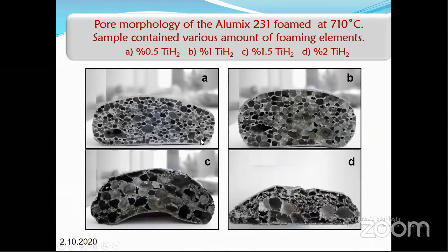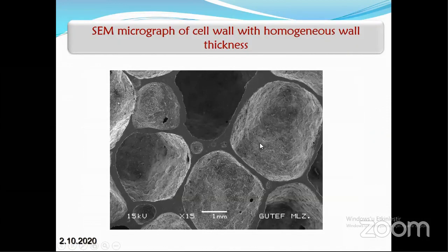This is the pore morphology of Alumix 231 foam at 710°C. Again, samples contain various amounts of foaming elements: 0.5% titanium hydride, 1%, after that 1.5% and 2%. Because of the high temperature and high amount of foaming elements, some collapsing happened, and we took these samples out, and they cannot be used. This is the electron microscope image of the cell wall, of homogeneous wall thickness. Look at this one. They are very good wall thicknesses.